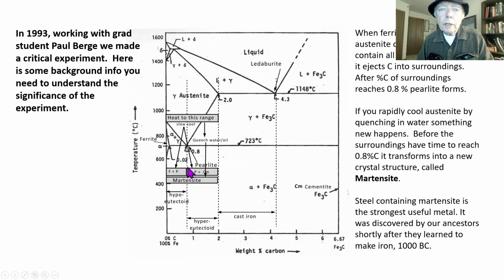Over here, if the percent carbon is below 0.8, you'll get ferrite and pearlite forming, and over here you'll get cementite and pearlite. Why? Well, think about what's going on. If you go from over here, the austenite will cross this line, start to form high purity ferrite. That'll cause the remaining austenite to increase in carbon, and it'll eventually increase to the point where pearlite forms. Over here, however, above 0.8, just the opposite happens. When you cross the line, the first stuff to form is this cementite, and it contains a ton of carbon. So that means the remaining austenite's carbon drops. Then you end up with pearlite and cementite. Okay?